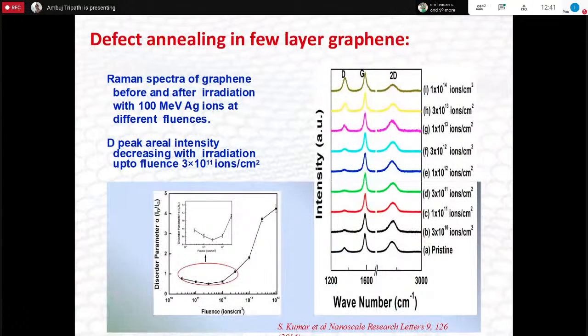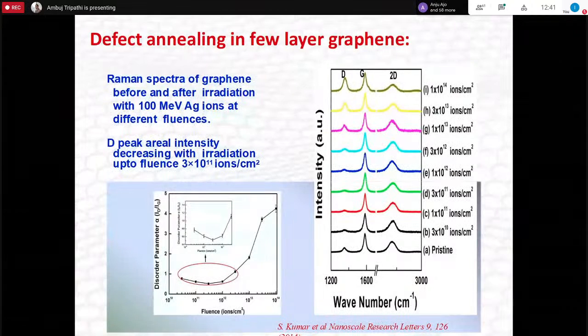So finally we tried to get the radius for the core, and the outside, which is this halo. So we gave this name core and halo. We said the core will do the damage, and the halo will do the annealing. As you see in the first curve on the bottom side, initially the damage goes down. On the right side, what you're seeing are the Raman spectra. There are three peaks showing D, G, and 2D. If you look from the bottom, which is unirradiated, and go towards the top with increasing fluence, you will see the D peak in the first three cases slightly goes down and then increases. The D peak generally relates to damage, and the ratio of these two will tell you whether the damage is increasing or decreasing.